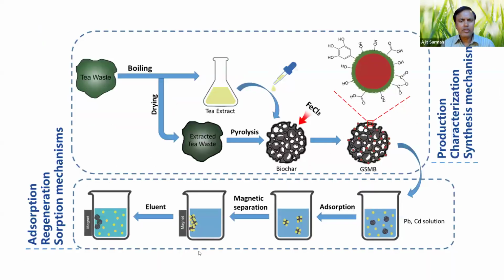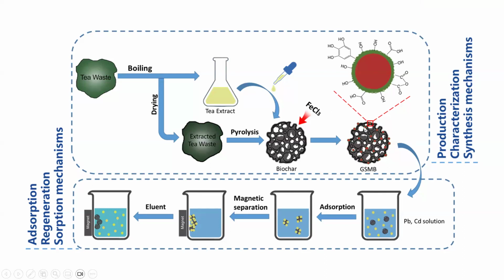This was done by one of my PhD students, Na Zhang. She looked at the removal of different types of heavy metals from aqueous solution using biochar produced from white tea residue. This is the way she did it. She boiled the tea waste, dried it, and extracted the tea waste. Then we did the pyrolysis in the lab, a small amount, at temperatures of about 450, 550, and 650 degrees Celsius. Then we added iron chloride, and then we got the biochar. This we then used for adsorption studies to remove different types of heavy metals from solution.